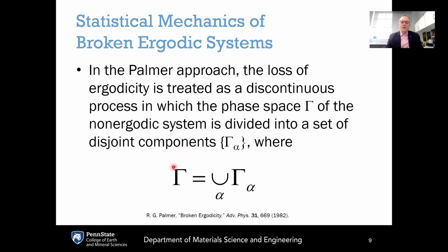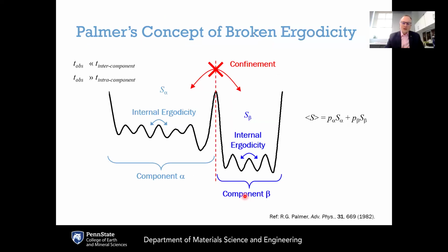So what Palmer proposed was that the entire phase space could be described as the union of disjoint components, where this alpha is meant to describe different components. And then these components represent regions where internal ergodicity is satisfied. For example, suppose that you have an energy landscape that looks like this, where you've got different configurations along the x-axis and then different energies along the y-axis.